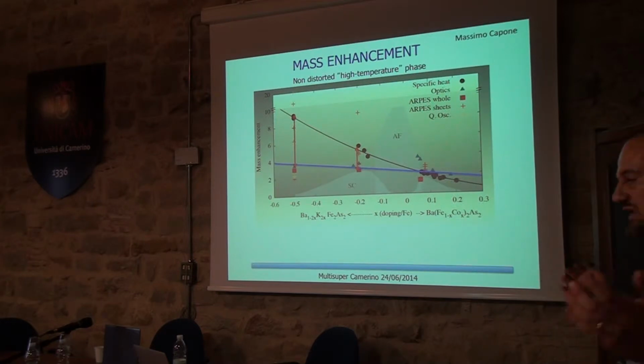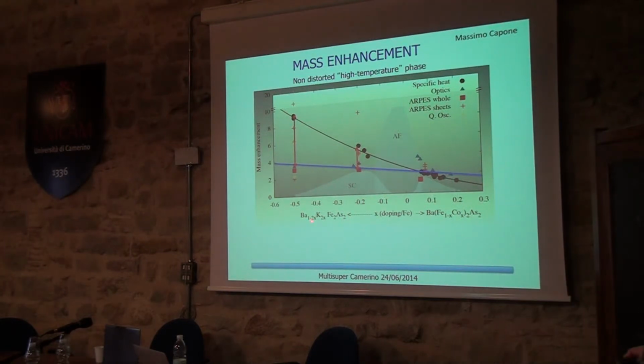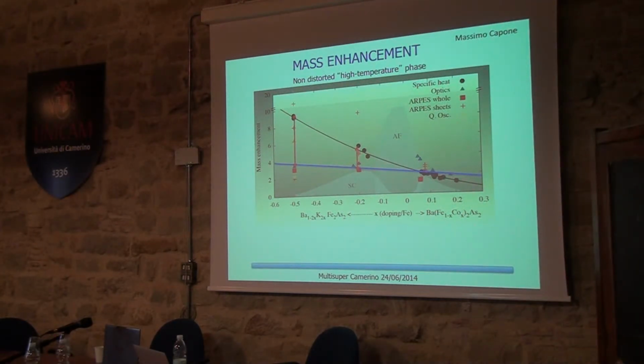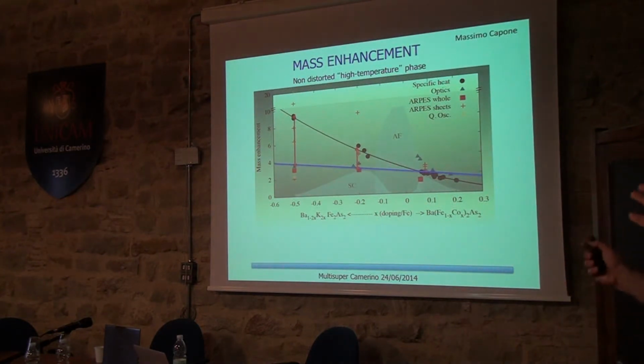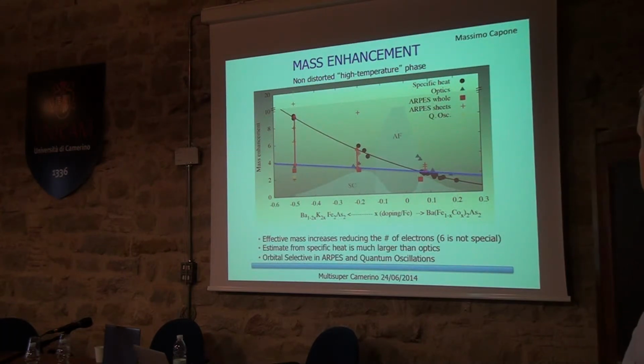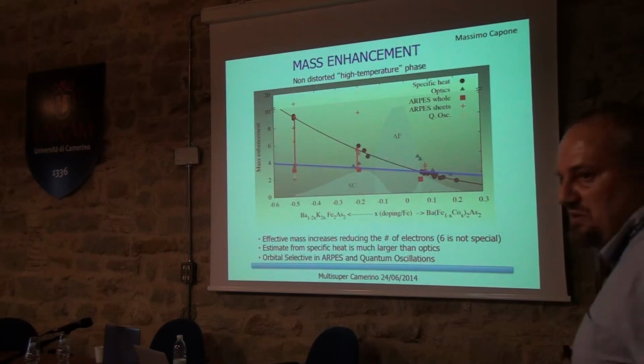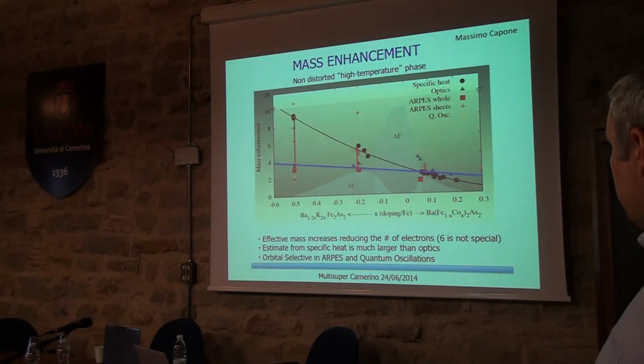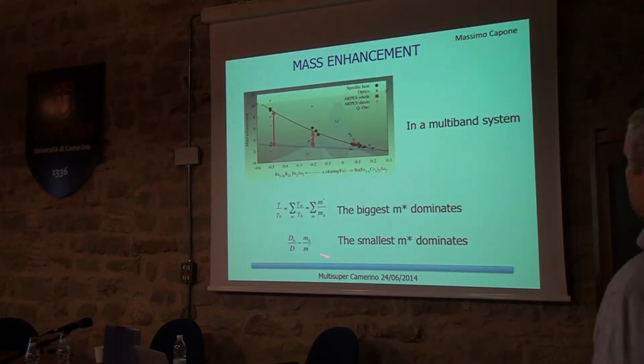There is a part of the electrons which gains a very large effective mass, with numbers like 9 that were mentioned before, and others that have a small enhancement like 2. So overall there is an enhancement, some average is enhanced, but it's very selective. And what we learn also is that 6 here, the parent compound, is absolutely not special in this light. The effective mass doesn't care about that region. Okay, so that's the summary.